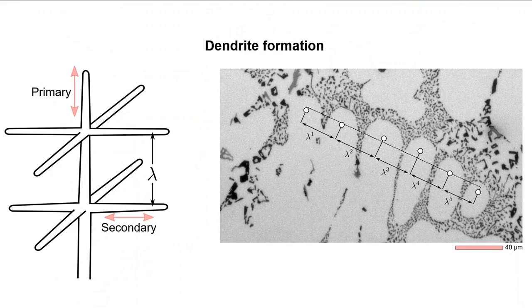Moving away from a 2D representation of a solidification front, we're ready to describe these mechanisms occurring in three dimensions. When undercooling is applied, many metallic systems will respond with the formation of dendrites. While nucleation and initial solidification will generate early grains as spheres, because there is preferred crystallographic orientation, at longer length scales, a dendritic microstructure will form. These appear as trees, if they're columnar, or globular clouds, if equiaxed. The trunks of the trees are primary arms, and from these extend secondary or even tertiary dendrite arms. The spacing between the secondary arms, shown here as lambda, can be correlated directly to cooling rates. What I've shown here on the right is what a random cross-section of a dendritic grain looks like for a cast aluminium alloy.